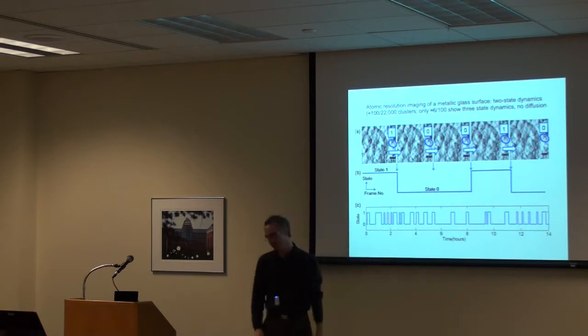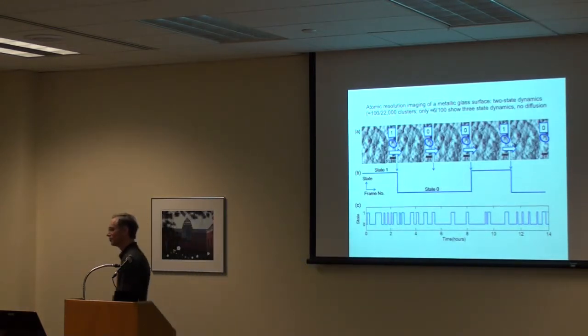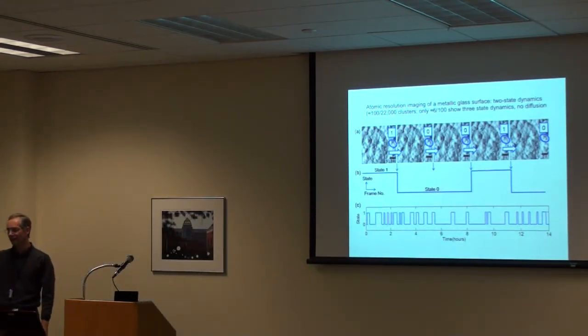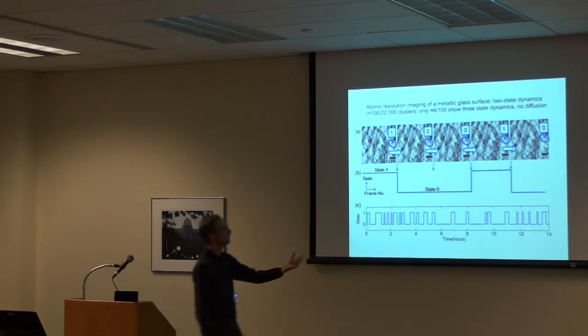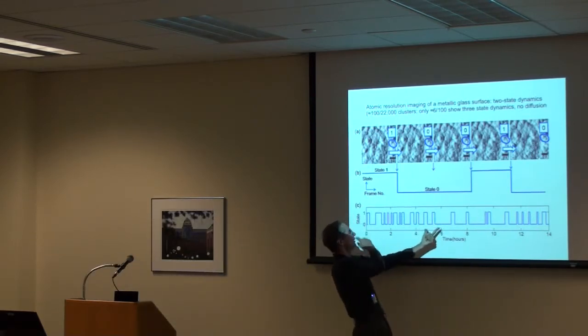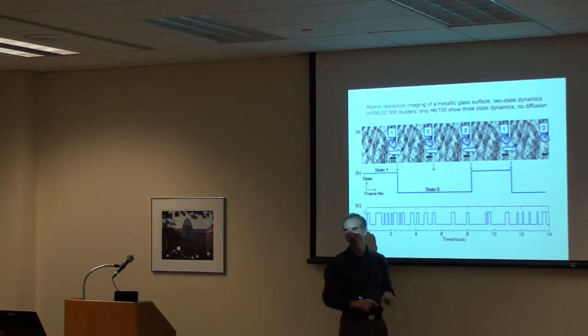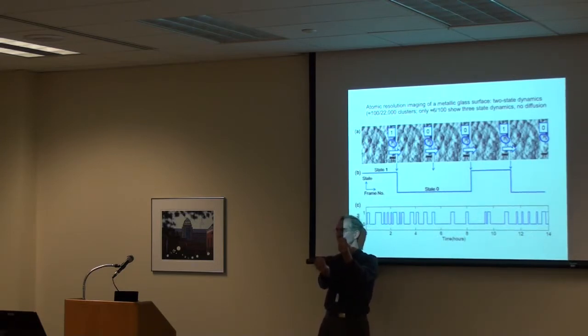And so we can actually get statistics on the kinetics of this motion. By analyzing these single cluster traces, you know, how much time does it spend on one side versus the other, we can actually determine both the rate of kinetics of going back and forth, and the equilibrium constant, right? Maybe one of those states is lower in energy, then it's going to spend more time in that state than it would in the other state. Like here, for instance, it tends to spend more time in the state that I call zero than in the state that I call one, which tells us that that state is a little bit lower in energy, right?